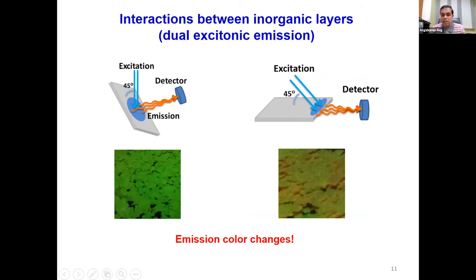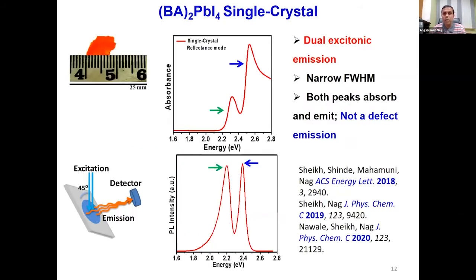To understand this change in the colors, we did some spectroscopic measurements. Here you can see these are the lead iodide layers, and this is butylamine. BA means butylamine lead iodide single crystals, and in these single crystals we cannot measure the absorbance because light cannot pass through the entire single crystal. So we measure the reflectance, and from reflectance we convert this data to absorbance, and you can see that it looks like there are two kinds of absorption peaks. Very interestingly, for both the absorption peaks, you see two emission peaks coming out. And when you look carefully, both emission peaks have their corresponding absorption.